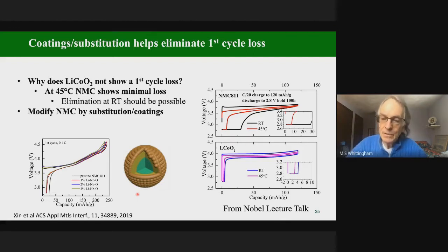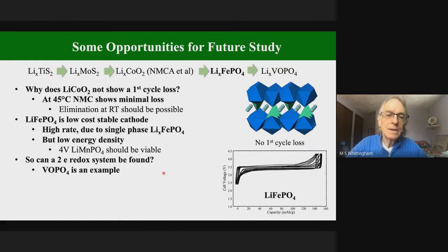Let me go back now to look at the history a little bit again. I started out with titanium disulfide. Moly sulfide was the next material looked at by Moli Energy in Canada. It went commercial for a few years, but had lithium problems. I've discussed lithium cobalt oxide. Lithium iron phosphate is the phosphate that John Goodenough looked at. It's a tunnel structure. There's no lithium loss, no first cycle lithium loss in this material, so we know it's possible even in a one-dimensional tunnel structure.